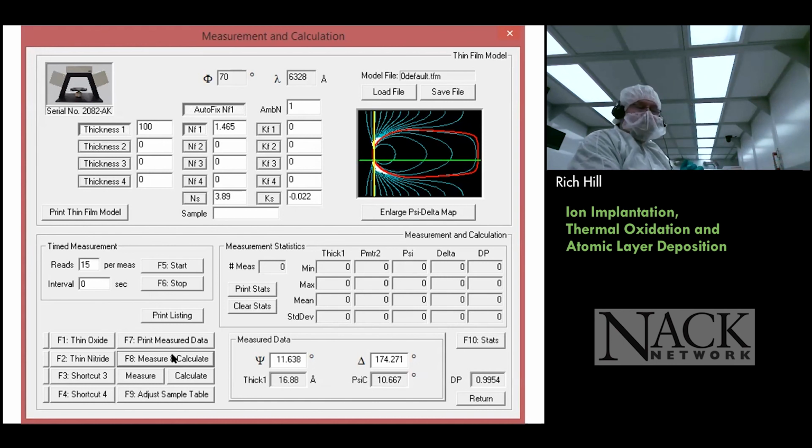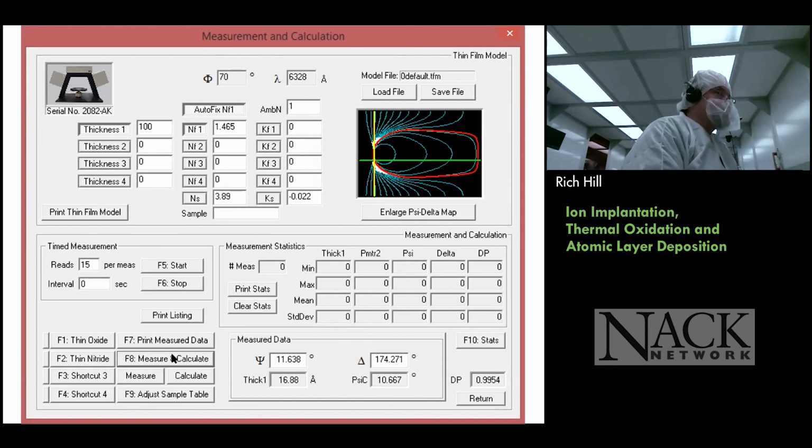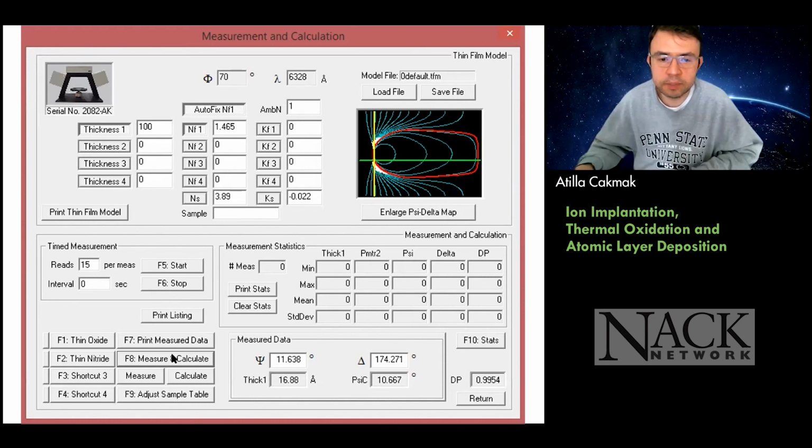I started out with a little bit thicker oxide layer, but I went from about 7 point something, then after I ran 15 cycles and put it back on, I had about 17 to 18 was my numbers. So yeah, it was very repeatable once I knew what number of cycles I wanted. Great. Yeah. So that's about it.